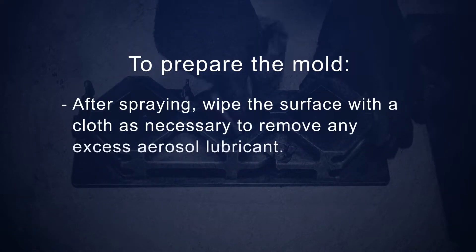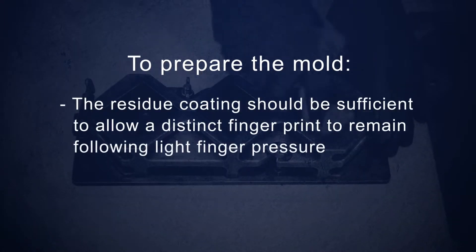After spraying, wipe the surface with the cloth as necessary to remove any excess aerosol lubricant. The residue coating should be sufficient to allow a distinct fingerprint to remain following light finger pressure.